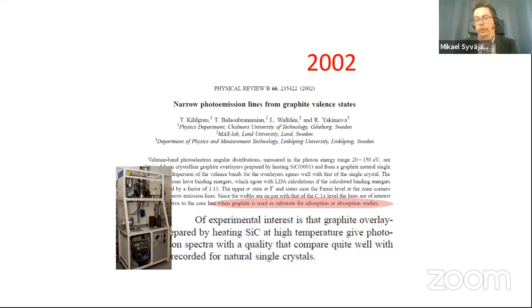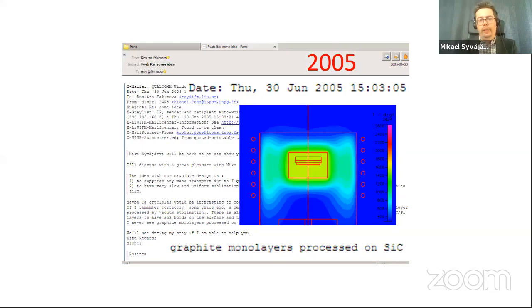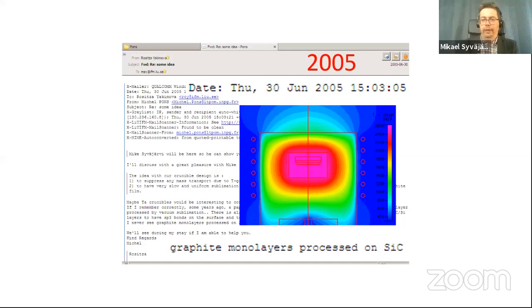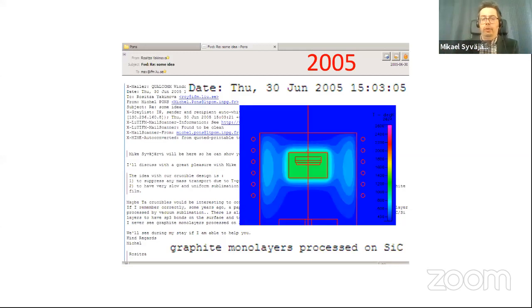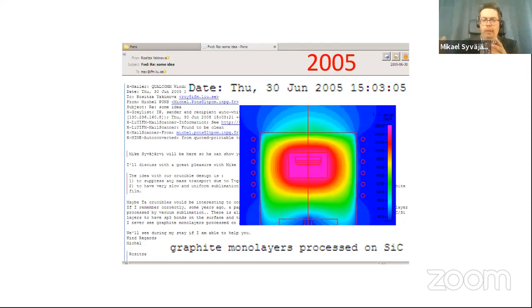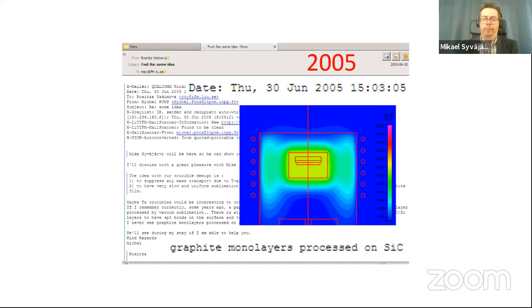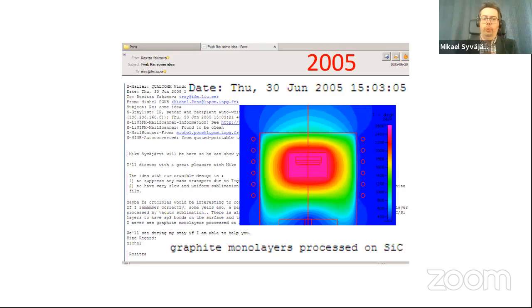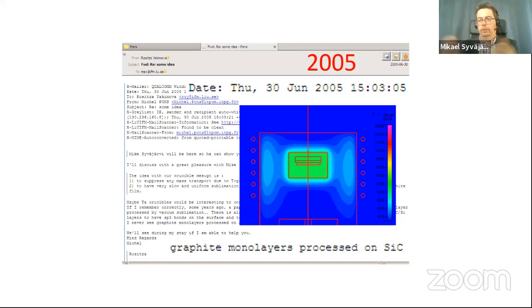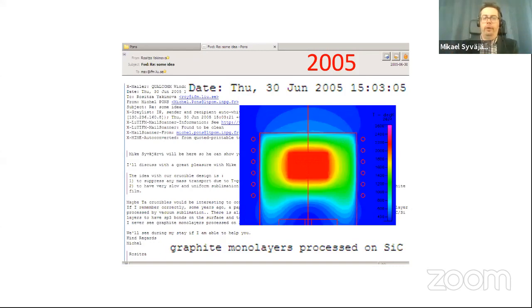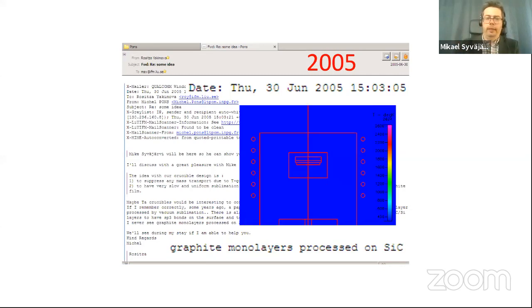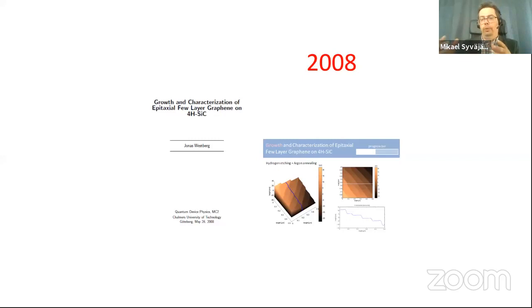There were a couple of publications in collaboration with Chalmers. And as curious researchers, we continued to explore the process, and we made the graphitic layers thinner and thinner and thinner. So actually in 2005, we had one layer of carbon. So a very thin graphitic layer, but that is actually graphene. So we had that result, and we asked some people, can you simulate the high temperature process so we can maybe understand more? But we did not know what to do with this. It was curiosity, and graphene was not hot at that time. But from the growth curiosity point of view, we started to explore this. And then there were young students coming to do master thesis works towards this avenue. So we further explored the process and started to have it more reproducible.